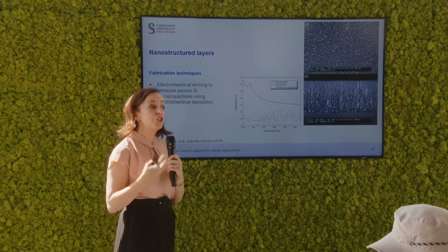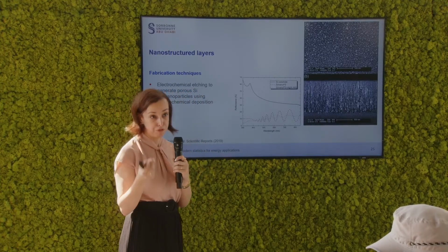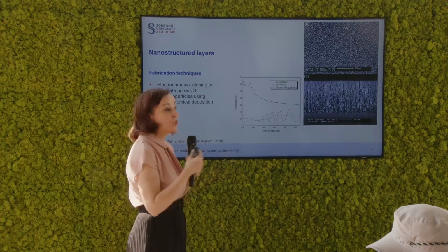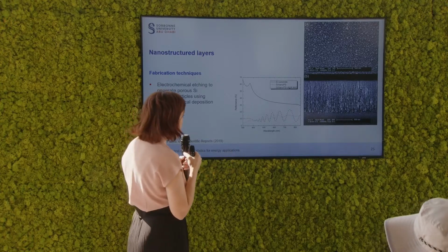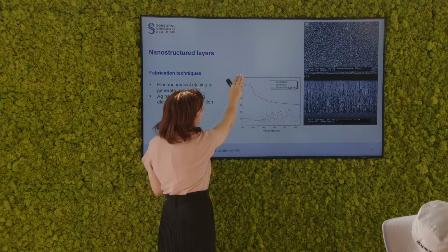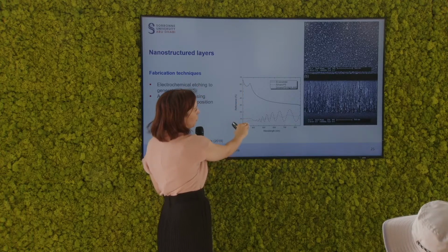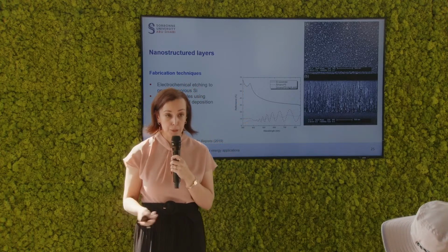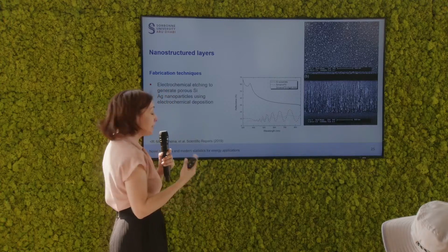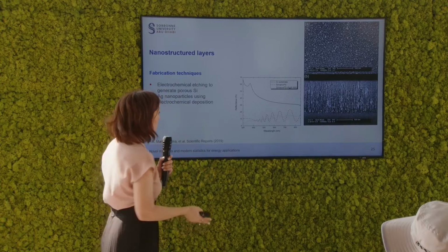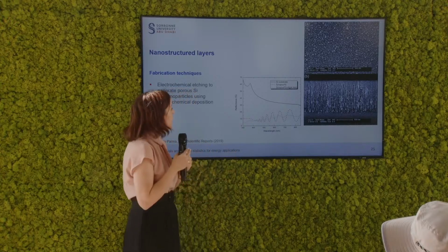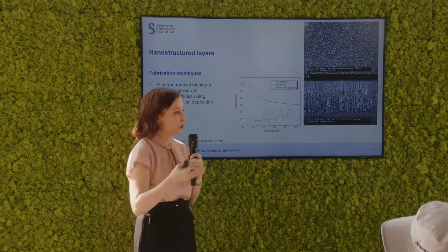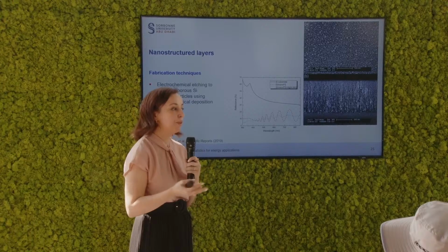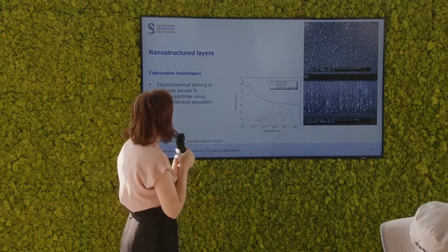This has already shown an improvement when it comes to the reflectance. As it is subjected to optical light, your reflectance from the pure silicon substrate will drop if you have nanostructuring on the layer. You can also incorporate silver nanoparticles in the process, which will further enhance the absorption. Lowering reflectance will automatically imply that you have enhanced the absorption of your material.